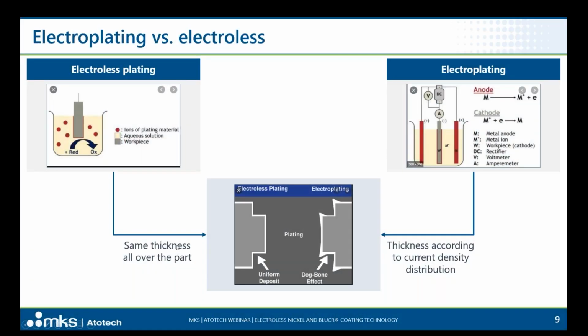If we have a look at the differences between electroplating and electroless plating technologies, we can see that in case of electroplating, we have in general a metal anode which dissolves with the current, as the metal cations will be reduced and deposited at the cathode, which is our substrate as well. The coating thickness is dependent on the current density distribution, and we can observe sometimes the dog bone effect.